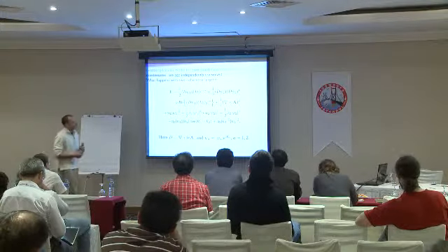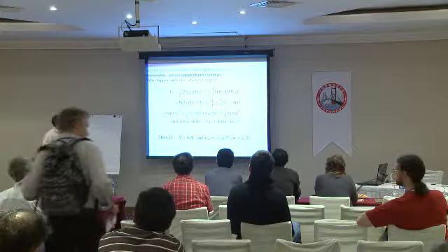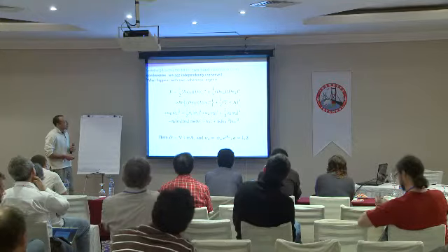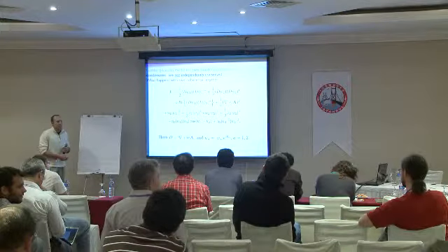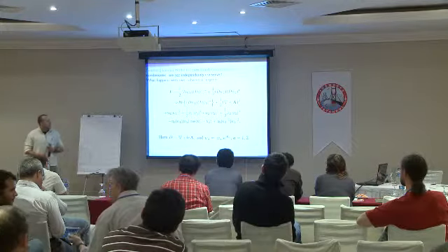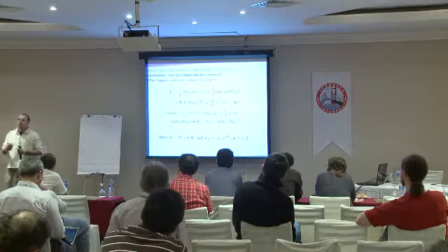All right. So what happens now if we consider two-band superconductors? The difference is that in two-band superconductors, interband interaction always breaks the symmetry down to simple U1 symmetry. And that means that there are a lot of terms which are allowed by symmetry, such as intercomponent Josephson coupling, interband pair scattering, mixed gradient terms of this form, and you can have other terms. And the question is how we define coherence lengths in that case. There is a lot of misunderstanding in the literature about how to define coherence lengths in two-band superconductors.